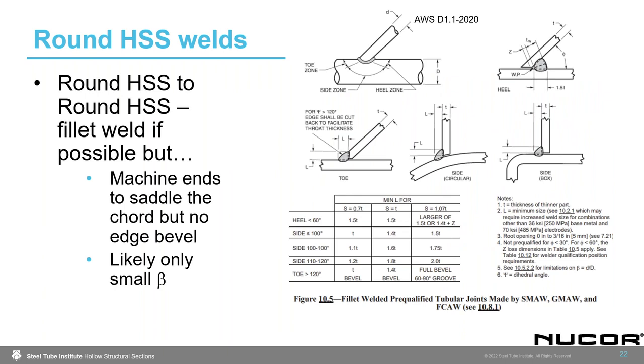Another thing to think about is if we're welding round HSS to round HSS, we know we want to try and stay with a fillet weld because we know that those are most economical. But it's likely going to be difficult to obtain the full fillet weld throat thickness. The dihedral angle of the joint needs to be maintained. This likely can only happen with a fillet weld if you've got a small beta, so a small ratio of the dimensions from the branch member to the chord member. So that dihedral angle needs to be maintained as between 60 and 120 degrees, which is kind of difficult.